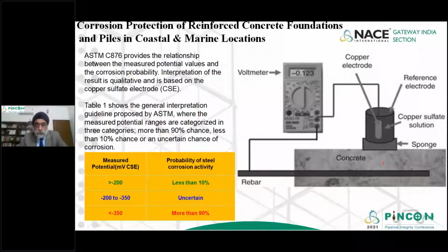So what we do is we take a sponge, we take a copper sulfate reference electrode, put the sponge on the concrete, put the reference electrode in a copper sulfate solution so that proper electrical connectivity is made between the concrete and the copper sulfate reference electrode. The copper sulfate reference electrode is connected to the multimeter the same way we would connect a pipe, and the rebar is connected to the positive of the multimeter the same way we would connect a pipeline. Now, the potential that we read, if the potential is